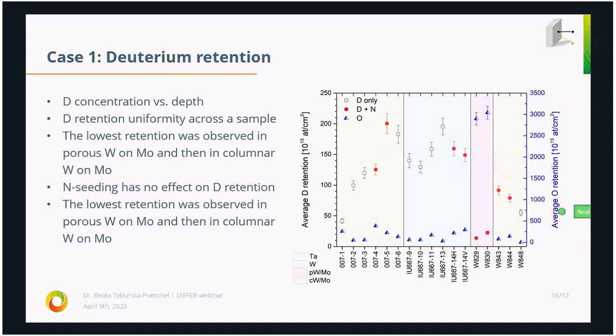I also plotted here on the right side the average oxygen concentration, which I got from the RBS data. And you can see that generally the oxygen level is more or less the same across all samples, except the porous tungsten. And maybe that's the reason why the deuterium retention in those heavily oxidized samples is so low, but this is still something worth analyzing.